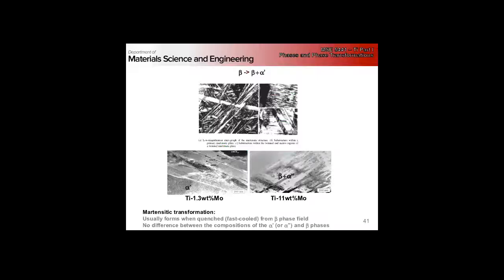A student asks if the TTT diagram looks similar. You do have the nose for alpha plus beta, but it's complicated because we can get omega phase and intermetallics — remember how messy the titanium-aluminum phase diagram got. The TTT diagram gets similarly complex. Conceptually it's very much the same, but titanium is generally not processed in the same continuous cooling way as steel, so TTT and CCT diagrams are not drawn as commonly for titanium, similar to how we didn't draw them much for aluminum.